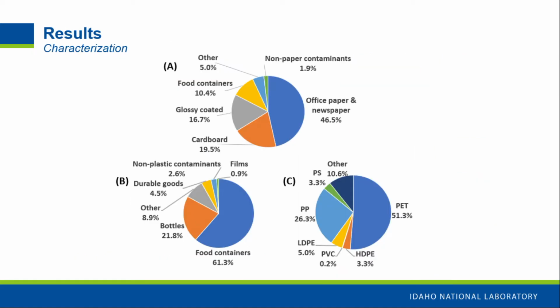And so I won't go too much into this, but we did a lot of characterization, hand sorting, and mass balance. The interesting thing that I do want to point out is in the very bottom two pie charts. The one on the right shows the kinds of plastics that we did receive. And the thing that I found interesting is that even though these are MRF residuals, the majority of the material is PET. So it is pretty contaminated. It is mechanically recyclable in theory, but it's still getting rejected from the MRF.